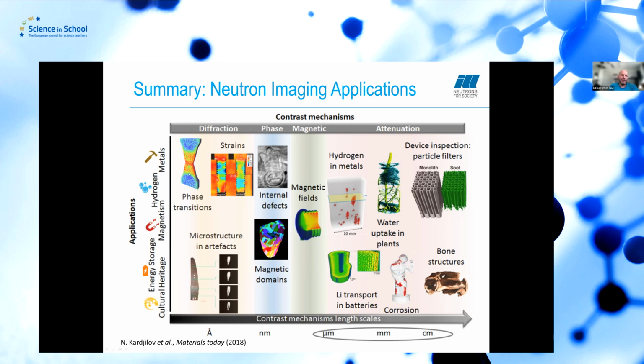And by combining it with diffraction in the monochromatic beam, we can have a look at strain. So there are Bragg edges that can serve to see phase transformations, or that we can then use to determine strain from the Bragg peak position changes in the sample. Or you can, for instance, have a look at the microstructure in cultural heritage artifacts. That is also a field where these neutron imaging methods are widely used. Our colleague Nikolai Kardjilov has made a nice overview on that, a review article in Materials Today.